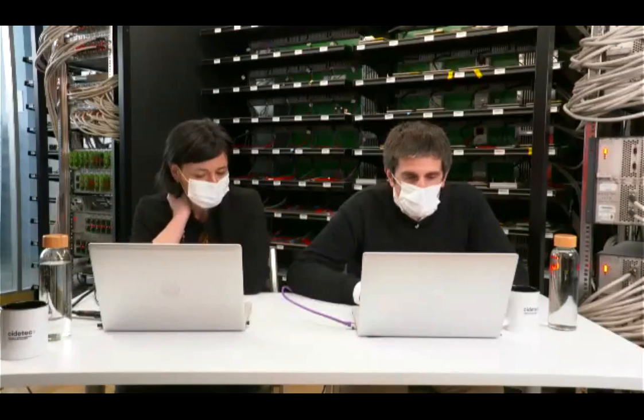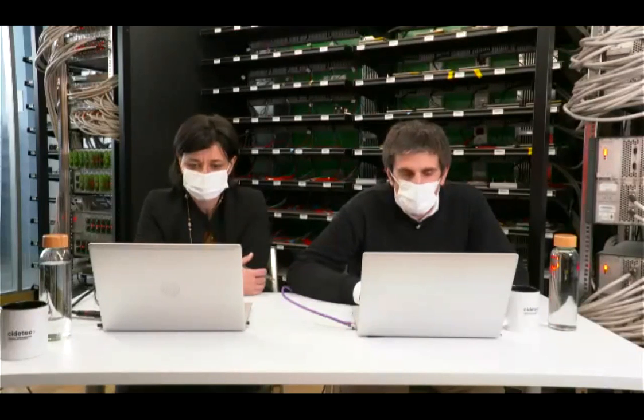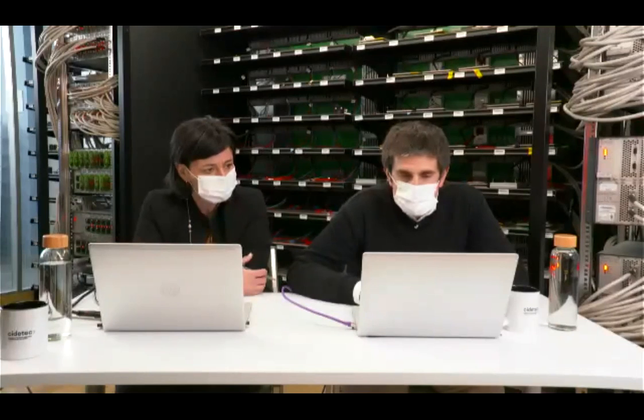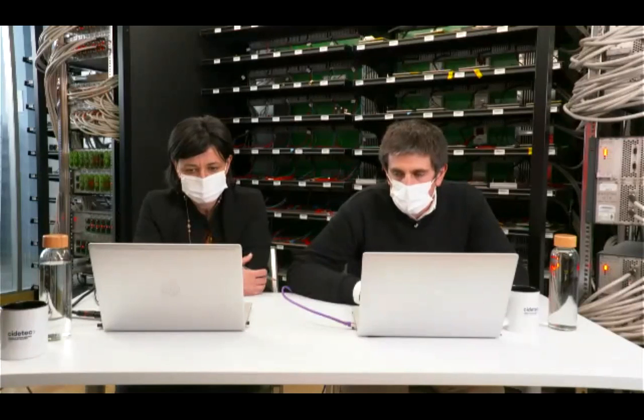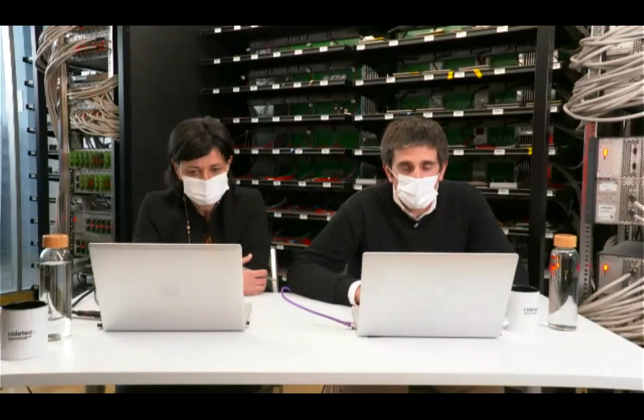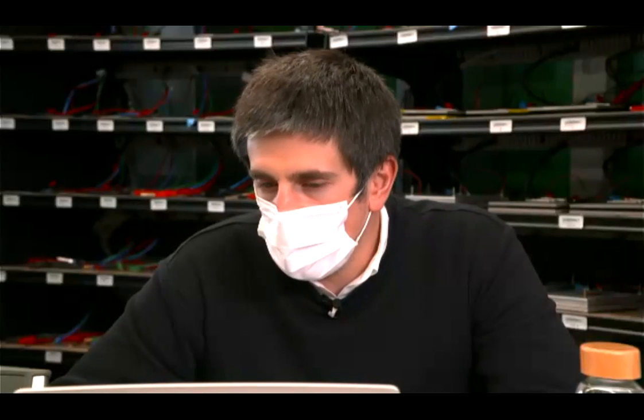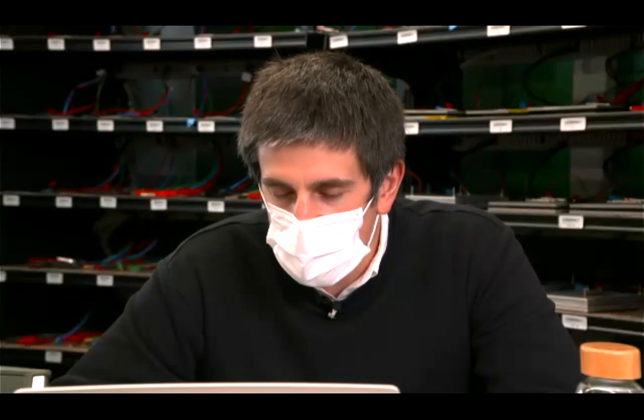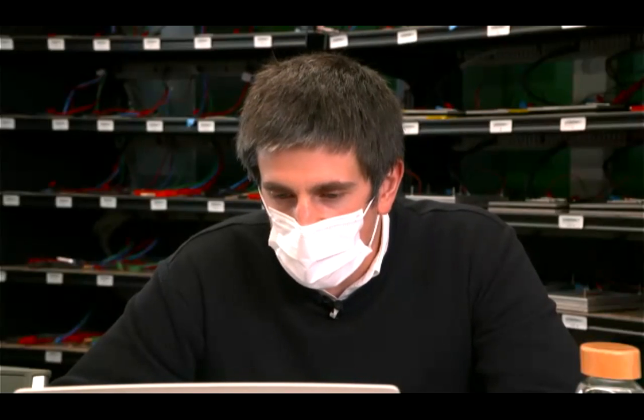Okay, the question is: what is the maximum temperature we are sensing with the thermocouple during formation? When we are checking this temperature, as we are doing the formation with low rates, the temperature of the cell is not increasing a lot. So maybe 1-2 degrees is the variation that we are seeing in the cell during the forming, but it's not a very big impact that we can see.